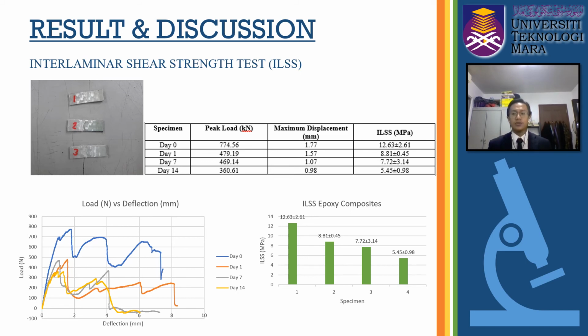This table shows the ILSS properties tests for the system. Generally, the material could not sustain and will break after the load exceeds the limitation of deformation of itself. We can see that the specimen with 0 day submerged in distilled water has a maximum load value of 774.56 kilonewton. It shows that the specimen at 0 days is higher in strength than the specimen at 14 days of submerge.